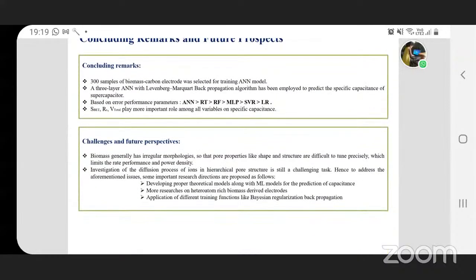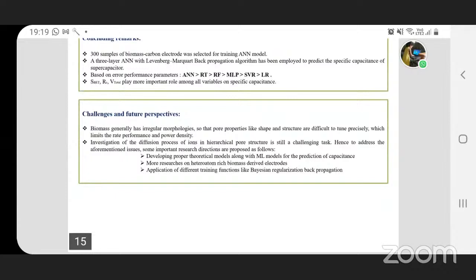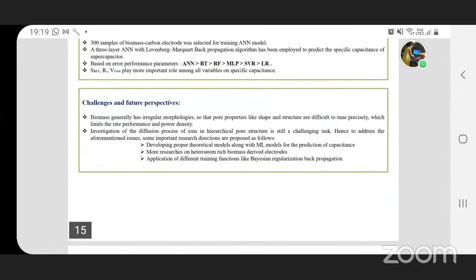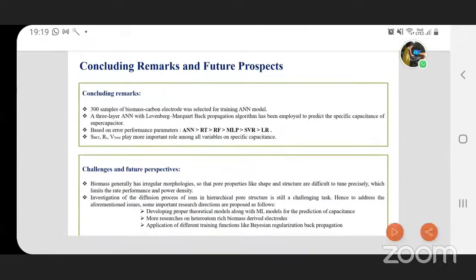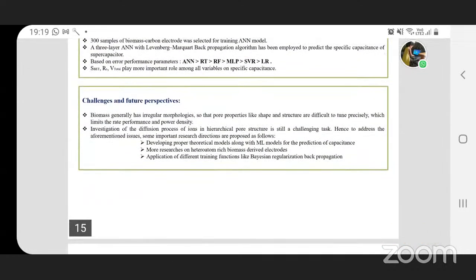So in my concluding remarks, we have considered a total of 300 samples of biomass carbon electrodes. We have trained it using the ANN model, and for the ANN, we have used the Levenberg-Marquardt backpropagation algorithm. And based on the error performance parameters, all these 6 models can be arranged in the following order. ANN was showing the best result compared to RT and RF, and the linear regression was showing the least correlation values. Out of all these, we found that surface area, internal resistance, and total pore volume of the biomass-based carbon electrode materials play a major role, and in respect of all other parameters, they were having more significant importance.